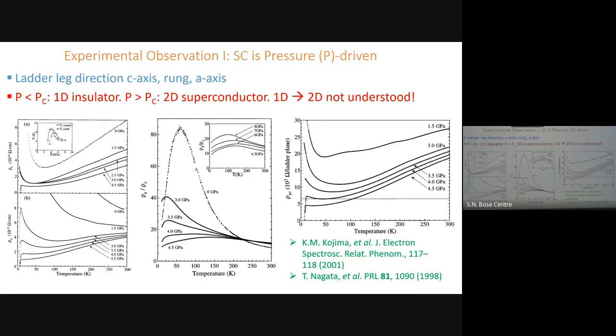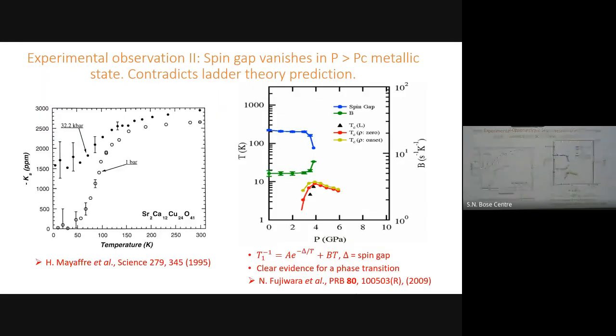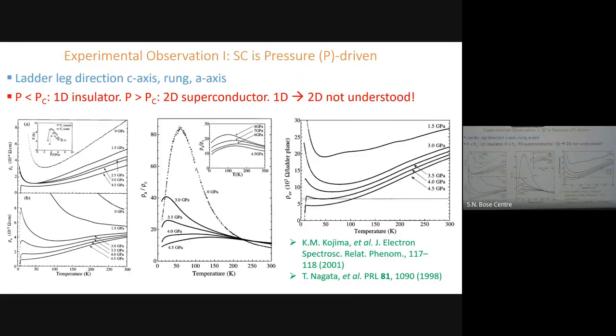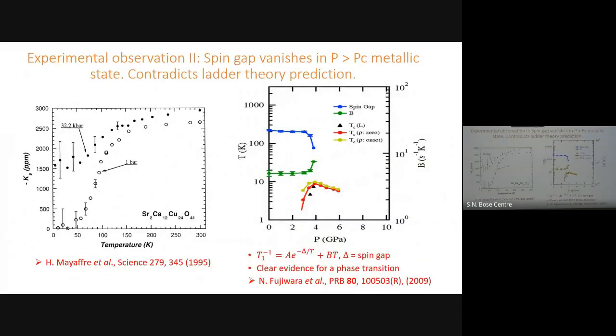And these people pointed out, I don't have time to get into that, that this behavior is very much like phase transitions in the opposite direction that are seen in the layered materials when you do zinc substitution. Superconductivity disappears right away and the resistance is the same. So it seems that there is a universal mechanism of two-dimensional insulator to superconductor transition. There are lots of other literature I can't get into, but this is a very interesting thought.